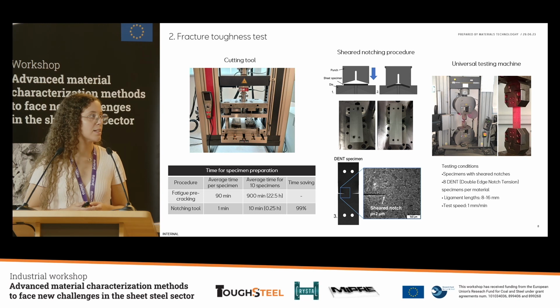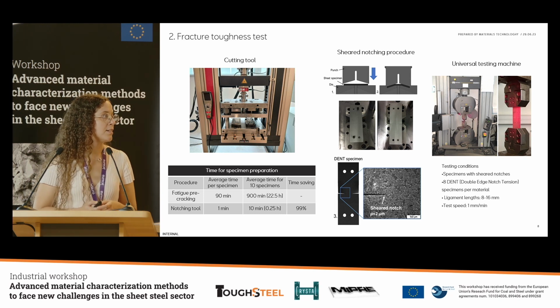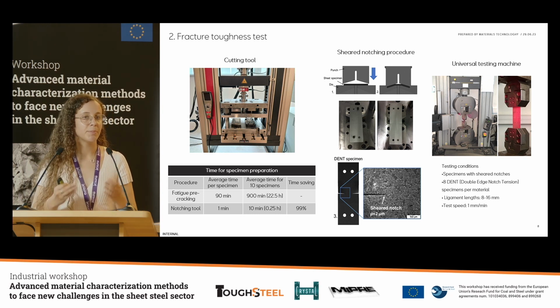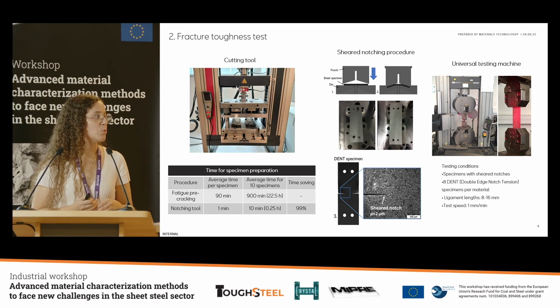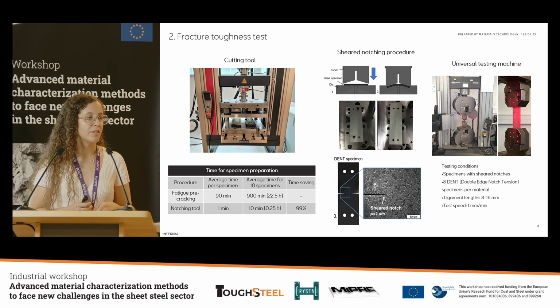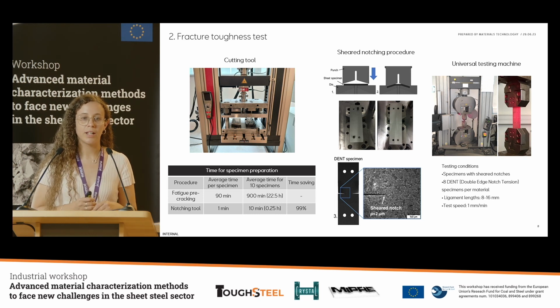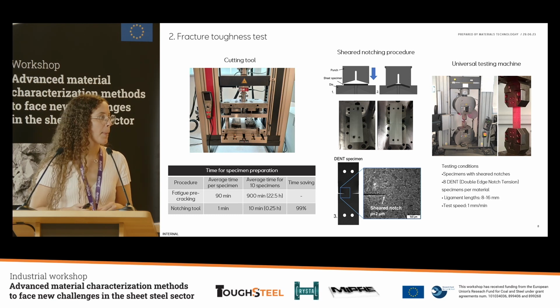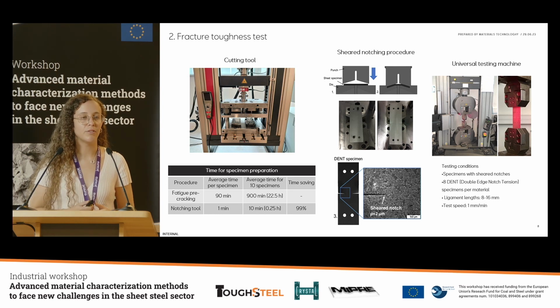while it would take more than 1 day to do it with fatigue pre-cracks. The system of this tool is that we have a bevel punch that, with a shearing process, can create these two symmetrical cracks. And we have a notch radius of about 2 microns. For fatigue pre-cracks, usually it's 0.1 microns, but we can adapt it, or we can trust the values for the essential work of fracture. Then we can do the test as usual with the tensile machine on the cracked specimen.